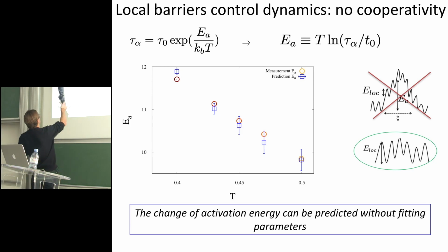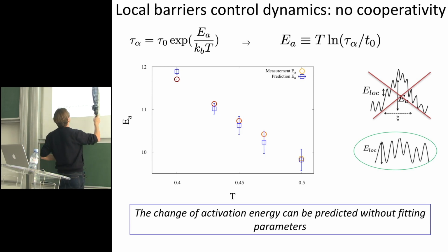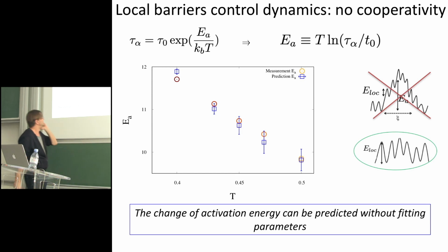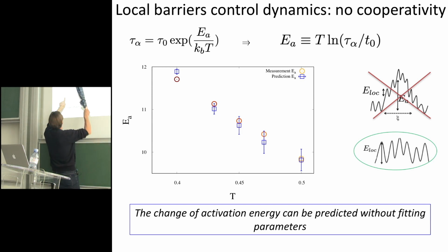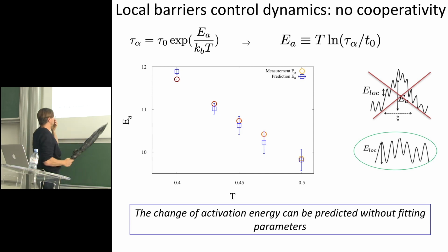What you measure doing molecular dynamics on those liquids is the relaxation time, and by inverting it, you can essentially measure the activation energy. This T0 is a microscopic timescale. In fact, we don't even fit it. We can measure it independently, and I could discuss how at the end of this talk. As you cool the system, those points correspond to the activation energy measured from the dynamics. And in blue, you have our prediction.